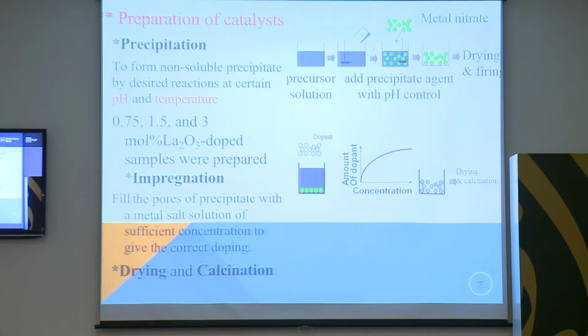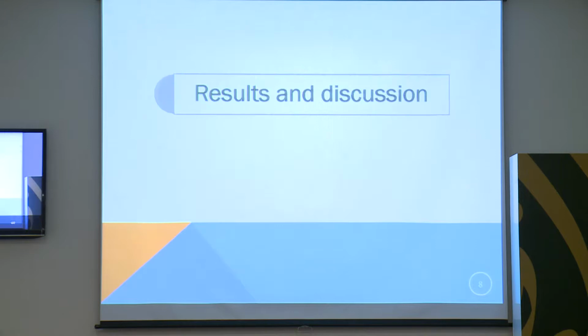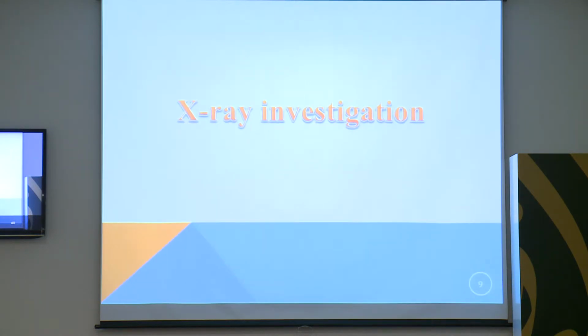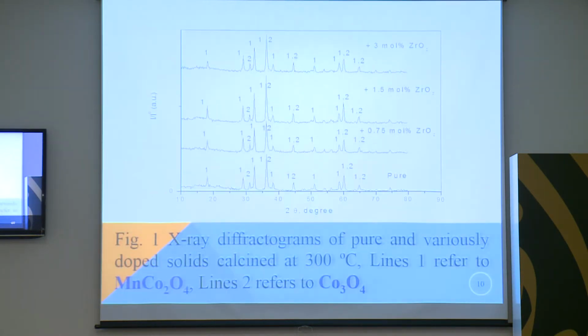After the sample completely precipitated, the drying process occurred at 110 degrees. The second step was to prepare the doped solids with lanthanum oxide at 0.75, 1.5, and 3 mole percent by impregnation method. The last step was the calcination for all pure and doped solids at 3 temperatures, 300, 400, and 500 degrees. The results and discussion, starting with the X-ray investigation.